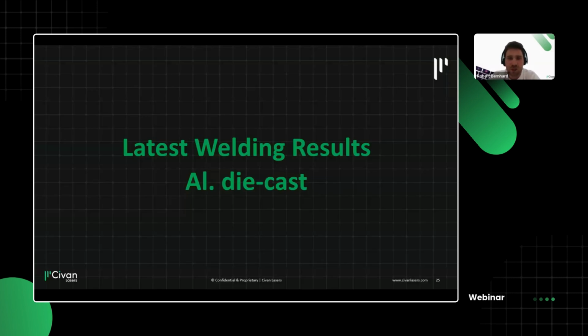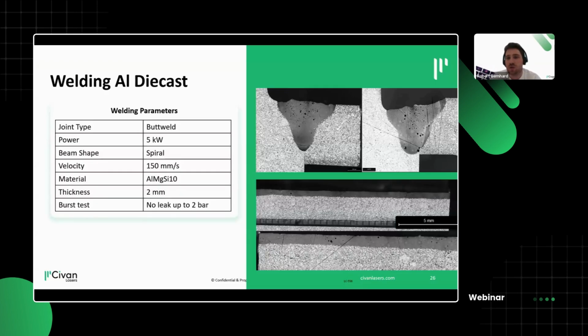And building on this, I think also a very nice application, and results we want to show, is the welding of aluminum die cast. The idea is to replace processes like friction stir welding, but also to replace long process chains where you have to mill your part and make perfect adjustments, when you can just use laser welding to weld raw aluminum die cast parts, straight from the casting ejected. So not much machining.